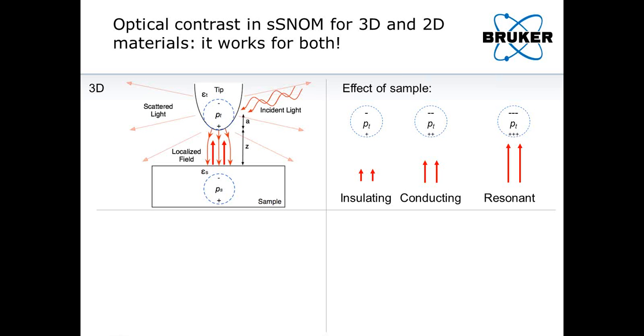I summarized that in three different cases on the right. For instance, if the sample is insulating, it will reflect a little bit less of the evanescent waves, as I indicated by smaller arrows, and then the tip dipole basically remains the same.